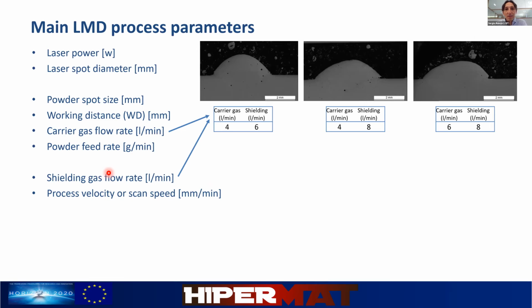And what we can see on these micrographs is that both the carrier gas and shielding gas have quite a big influence on the shape of the track. You can see here we have a clad with a bigger height, and just by changing the carrier gas and shielding gas, we can reduce this height.